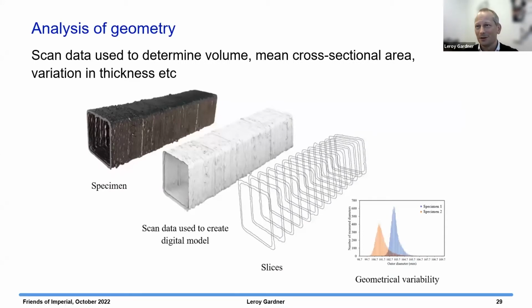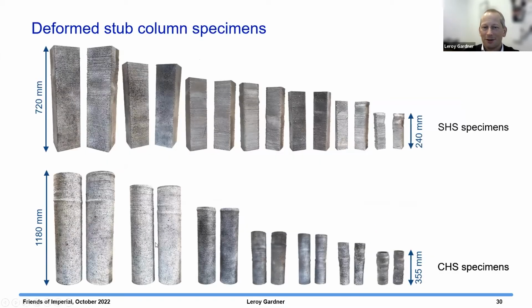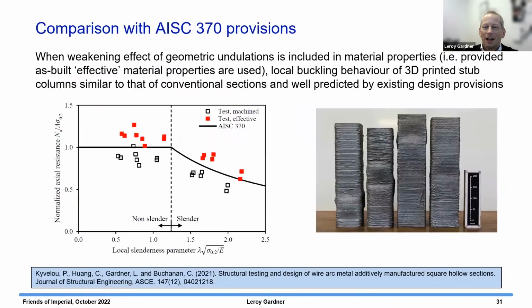And what that allows you to do is get really detailed statistical information about variation in diameter, variation in thickness. And this is important for later on when we're looking at safety, reliability, and so on. So we tested a series of different geometries, different sizes, different proportions. And we typically got, so these first ones are short compression elements, and you can see the failure modes here, which is called local buckling.